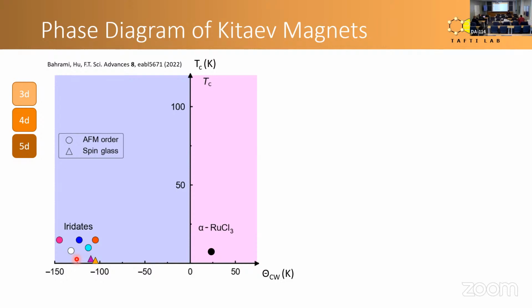Okay, then you also have ruthenium chloride. This one has a positive Curie-Weiss temperature. That is, it basically has a ferromagnetic exchange, but in polycrystalline material. It turns out the exchange can be very anisotropic in this system. So all the data I'm showing here is in the polycrystalline samples.